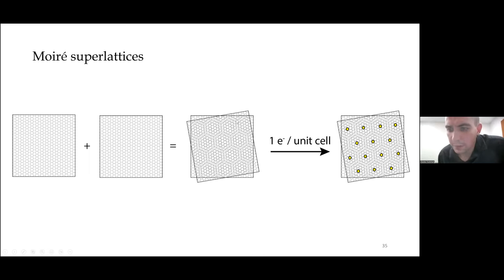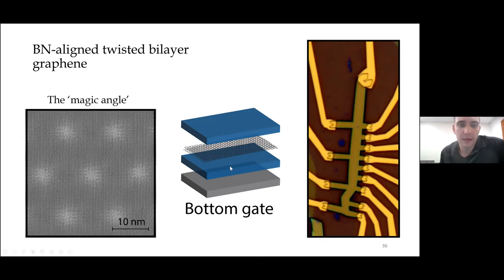So the first system I'm going to talk about is this twisted bilayer graphene system. On the left, I've shown approximately to scale what the magic angle twisted bilayer graphene moiré superlattice looks like. The unit cell is a little bit more than 10 nanometers. And these systems are all bilayers or trilayers encapsulated in boron nitride with a graphite bottom gate. So all of those steps are important for realizing low disorder systems. And an optical image of this device is shown.